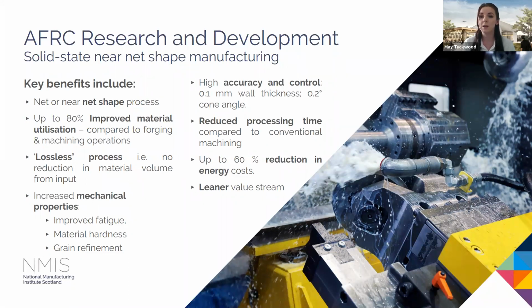The mechanical properties can be significantly improved also, from fatigue to material hardness and grain refinement. It's something that we're particularly focused on at AFRC, is understanding the component integrity, but most importantly, how that may compare to a conventional method. Many of the projects that we work on, they're targeting cost reduction, but it seems to be that there's often a conflict of requirements between designers, between business, like the business case for those parts, in terms of reducing that cost, and it seems to need a compromise on quality. Now, with the near net shape processes, you do get that cost improvement, but also we can see an improvement in the quality of that part. So it's a win-win, but I think the key advantage of working with us is that we've been working with design teams to try and then embed design for manufacture of these processes that hasn't been embedded previously to get the most optimal outcome.